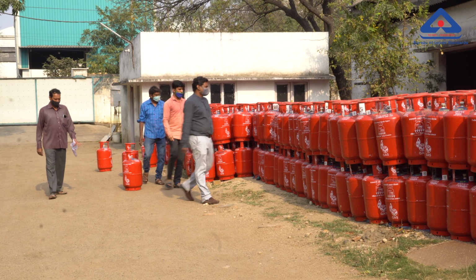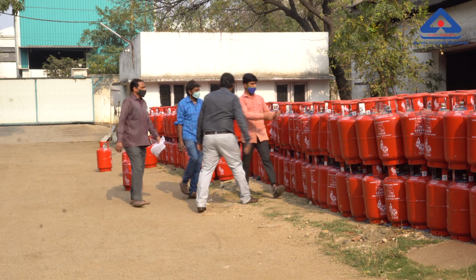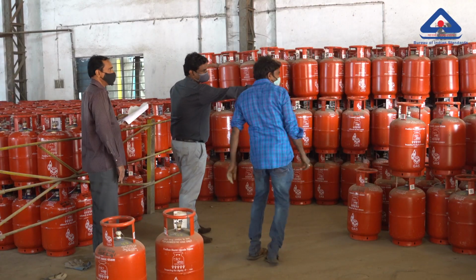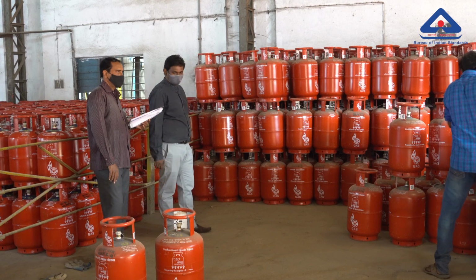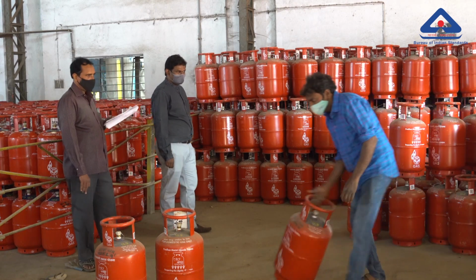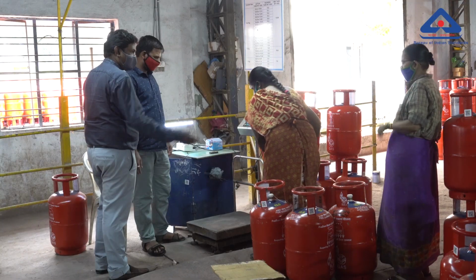Now, the cylinders are stacked batch-wise and are ready for BIS inspection before dispatch. During this lot inspection, BIS officer does the audit of each manufacturing process. As a part of acceptance test, different test pieces are cut from the cylinder for carrying out tensile test of the weld pieces, tensile test of the parent metal pieces, bend test, macro examination and minimum thickness. The yield strength, tensile strength and elongation of the test specimens are the critical parameters tested here.